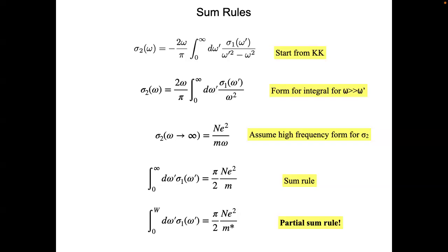If that W is some really low energy manifold of states, which may be relevant for a system like a heavy fermion, where I have a really low energy coherence scale and perhaps a very narrow band which forms in response to a Kondo interaction, and so that omega is a really small value, then I'm going to pick up a very small number on the right, which corresponds to a large mass, which is what I would get in a heavy fermion system. So that's one thing I could do.